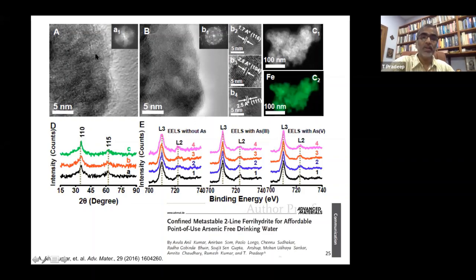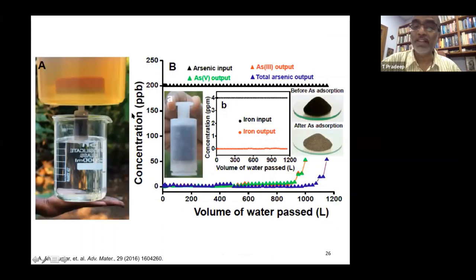And this iron oxyhydroxide, if you can make it into a particular kind of form, a metastable form, it has large adsorption capacity for both arsenic 3 plus and arsenic 5 plus. The material as you make it is amorphous or nearly amorphous, but under an electron beam, it crystallizes, and you can see tiny crystallites, very, very tiny. And this is an expanded view of that, something like 3 or 4 nanometers or so. And these can be characterized in great detail with a number of spectroscopic techniques. And they have large capacity, as I told you.